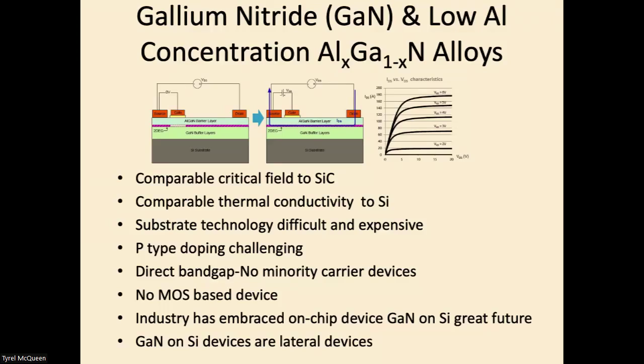Gallium nitride is usually made competitively on a silicon substrate, although single crystal GaN substrates are becoming available. They're really quite immature and costly. But right now, you can grow good quality gallium nitride devices on silicon substrates, but it's really not just gallium nitride, it's gallium nitride and low-X aluminum gallium nitride using polarization induced doping. This device is a lateral device, which causes problems, but is workable. That has a comparable field to silicon carbide, some say a little better, and comparable thermal conductivity to silicon.